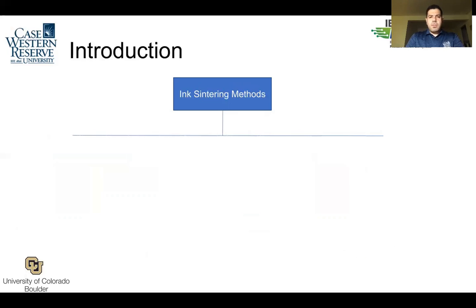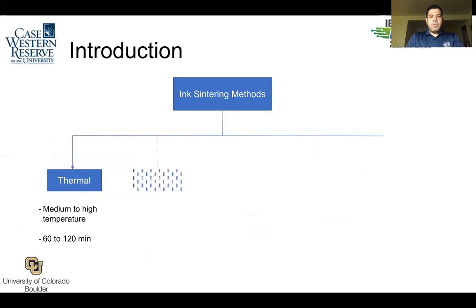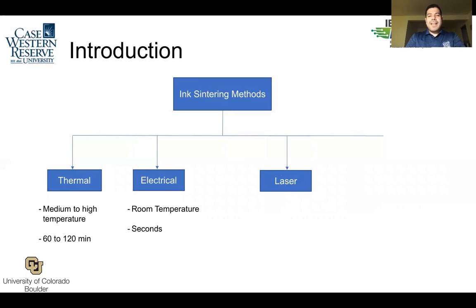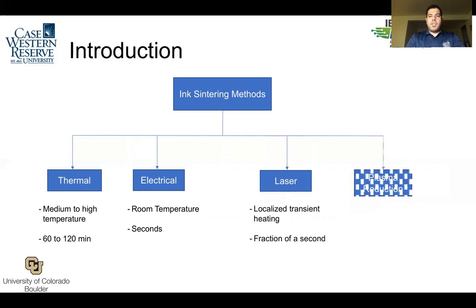What are the ink sintering methods? Very quickly, you have thermal sintering, medium to high temperature, takes an hour or two. You have electrical sintering, it's done at room temperature, but takes seconds, that's faster than thermal. There's even faster than electrical, which is the laser sintering. And it utilizes transient localized heating. And this laser sintering takes a fraction of a second.